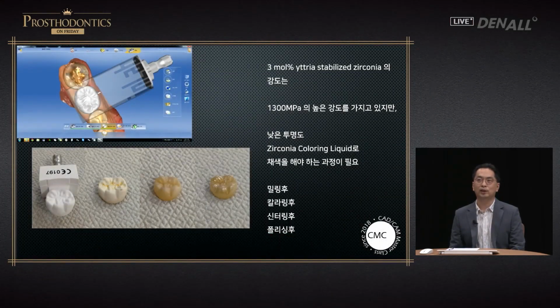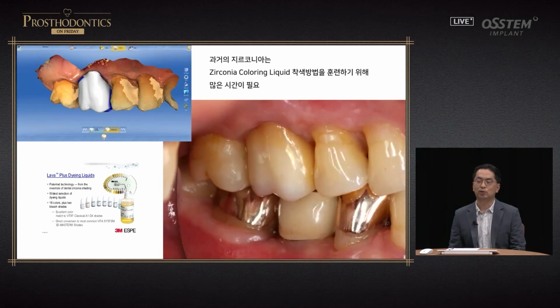In the case of 3 mole yttria stabilized zirconia, it had a high strength of 1,300 megapascal, but it showed low translucency, and in order to provide color, a coloring process was required. As you can see on the screen, the zirconia is white. After brushing and adding color, this is after sintering and polishing. In order to fabricate a zirconia crown, coloring liquid needed to be applied. It took me a lot of time to be able to do a good job using this.